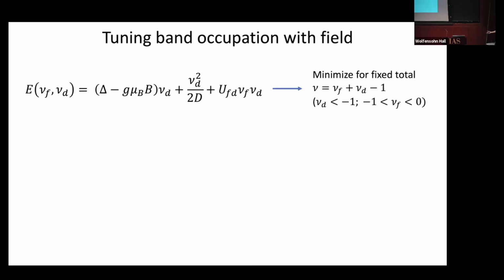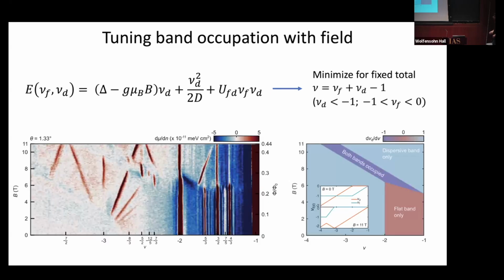So we can cook up a simple model for the free energy of this sort of system. It takes into account some effective Zeeman energy splitting between the 2 different types of bands, the s orbitals and p orbitals. There's some density of states associated with the dispersive bands, and we put in some sort of Stoner type interaction between carriers in the flat and dispersive bands. And you can just ask a very simple question. For a given filling factor, if you try and minimize the simplified free energy model, what do you get out, theoretically? What do you expect? And so that's what's shown here in this schematic diagram. And already you can see that there's a good correspondence between the experimental data that we observe and this theoretical prediction from this simple model. That is, in this region here where you have low magnetic field and low filling factor, you expect to occupy the second flat band, this other s-type orbital.